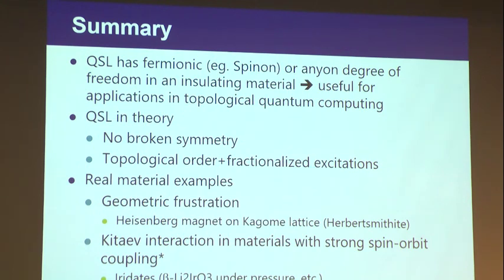But in a real experimental situation, what I'm emphasizing here is that you need to find a material which doesn't have magnetic order, and you can achieve that through geometric frustration or inherent interaction frustration through Kitaev interaction. There is one known candidate for quantum spin liquid, which is herbertsmithite. And for Kitaev quantum spin liquid, there are a number of candidates, such as beta lithium 2 iridium oxide or ruthenium chloride under in-plane magnetic field or pressure. All these things are open questions that are actively investigated these days.